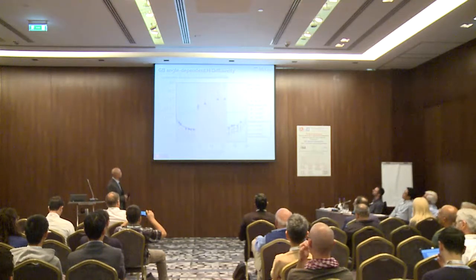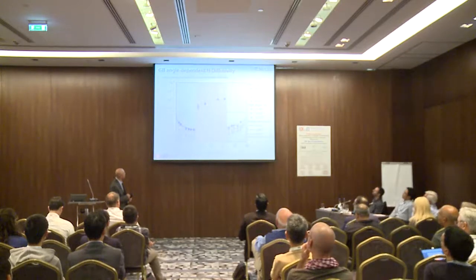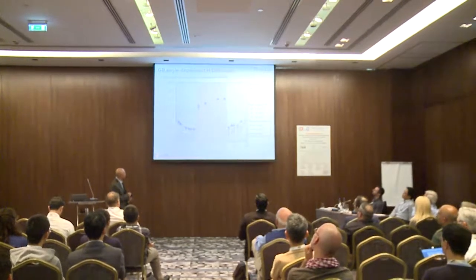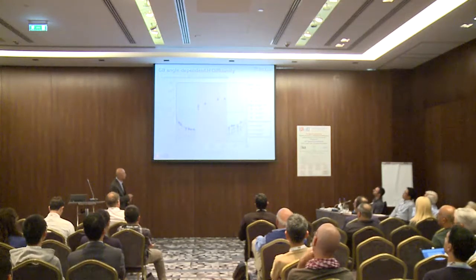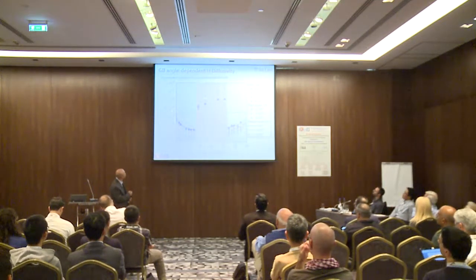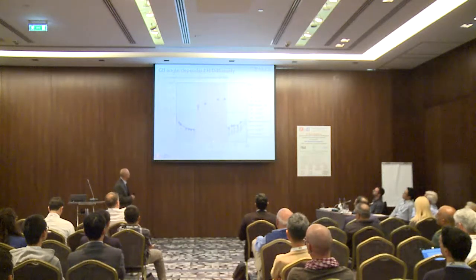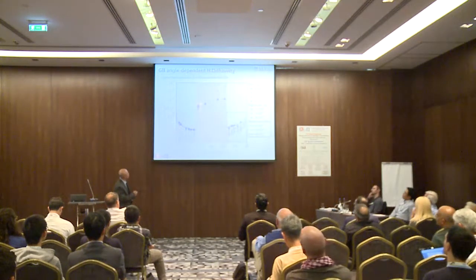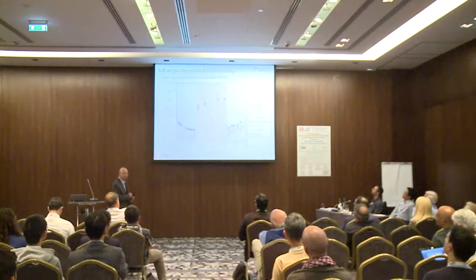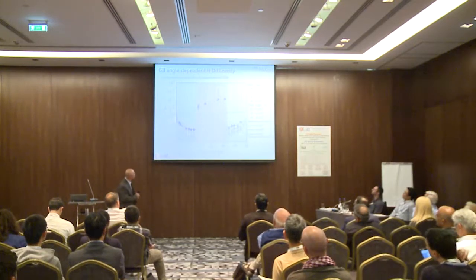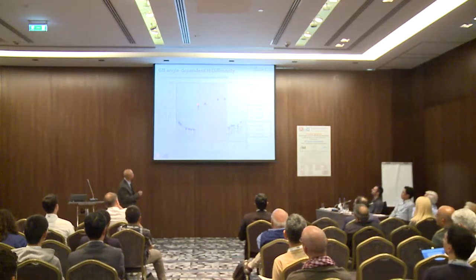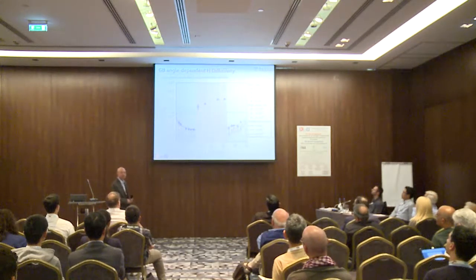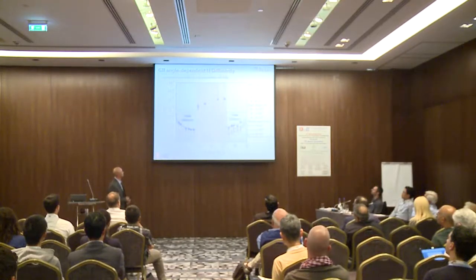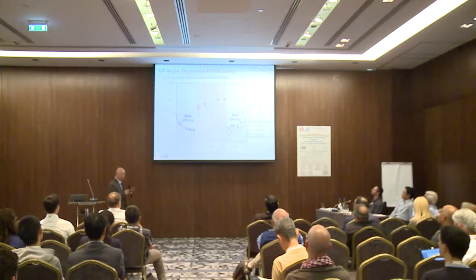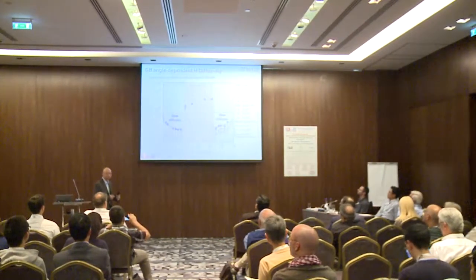Okay? And now if we plot the diffusivity for this set of grain boundaries, you'll see that as the tilt angle varies, for the left and right regions you have the diffusivity much lower than the bulk diffusivity. Of course, it depends on the bulk concentration. And in the middle, you have actually much higher diffusivity. Okay? So you see there's a systematic variation of the tilt angle, and you see two drastically different diffusion scenarios. There are two slow diffusion regions, we can call it slow diffusion, while the middle is fast diffusion.